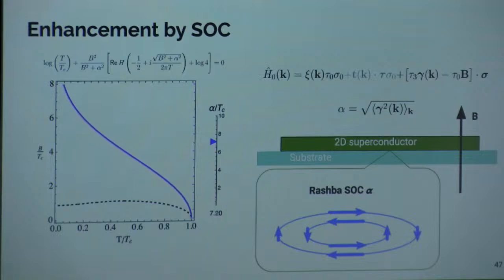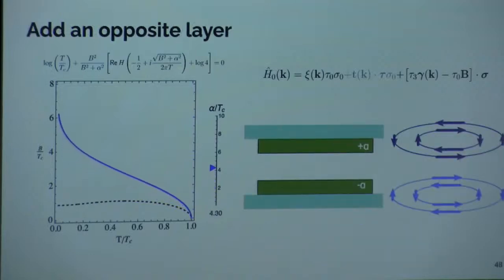So because of Rashba spin-orbit coupling, now the magnetic field has a harder time destroying superconductivity. So you see the larger alpha, which is spin-orbit coupling, the greater the critical field. Now add another layer, but invert it, so that globally there is inversion symmetry, but locally on each layer you break inversion symmetry. Of course, since they do not couple, the phase diagram is identical.